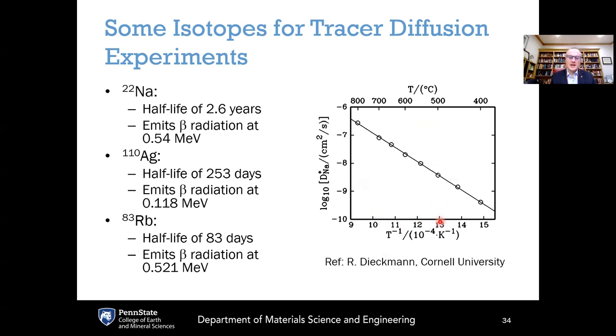This shows you an example. This comes from Professor Rudiger Dieckmann, who is now retired from Cornell University. This shows the self-diffusion of sodium using a sodium-22 isotope, which has a half-life of 2.6 years and emits beta radiation at 0.54 mega electron volts. You see plotting it versus inverse temperature, you get the straight line here.